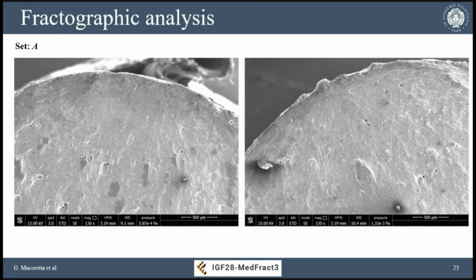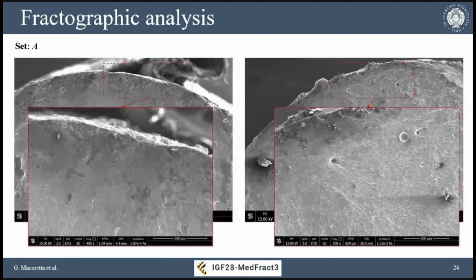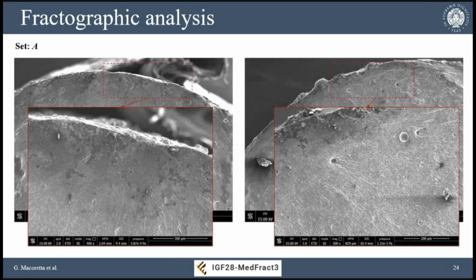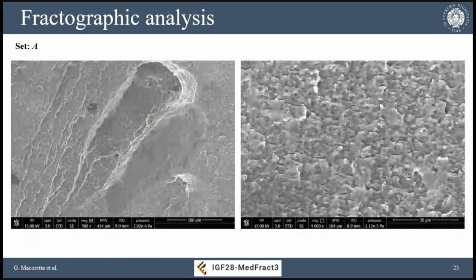Just to conclude, the fractographic analysis - what happened to our specimens, what is the killer defect? For the A set, the killer defect, as you can see here, was surface roughness. The crack originated from the surface and propagated from surface roughness valleys, both in circumferential and longitudinal direction. Also when we have some subsurface pores, the fracture started from surface roughness valleys that were near subsurface pores, increasing the stress a bit in that region.